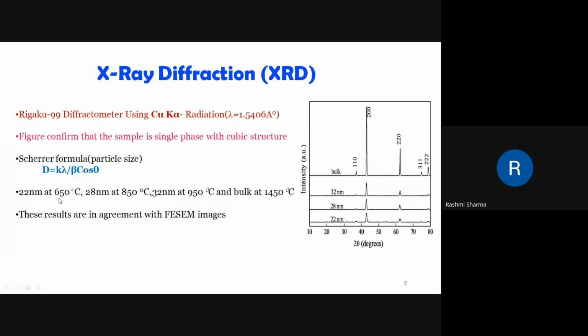For example, for particles calcined at 650 degrees Celsius, we get the size to be 22 nanometer. For the particles calcined at 850 degrees Celsius, we get the size to be 28 nanometer. And for 950 degrees Celsius, we get the size as 32 nanometer. And for particles calcined at 1450 degrees Celsius, we get a bulk sample. We do not get a nanoparticle, but we get a bulk sample. These results are in agreement with FESEM images, field emission scanning electron microscopy images.